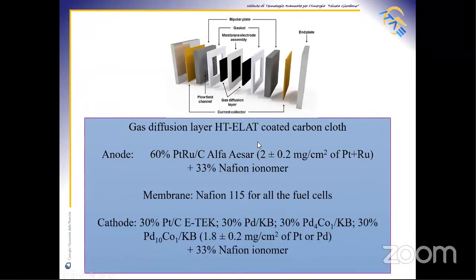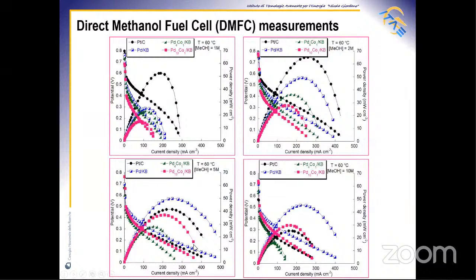For the fuel cell measurements, we compared the prepared palladium-based catalysts with the benchmark platinum carbon used as cathode catalyst of four different membrane electrode assemblies. Platinum ruthenium carbon was used as anode catalyst in all the fuel cells, and MEAs were obtained by the hot pressing method between electrodes and Nafion membrane. Different methanol concentration solutions were fed at the anode, whereas oxygen was fed at the cathode. The performance of each MEA was measured at 60 and 90 degrees. In this case, we report just the measurement at 60 degrees centigrade.